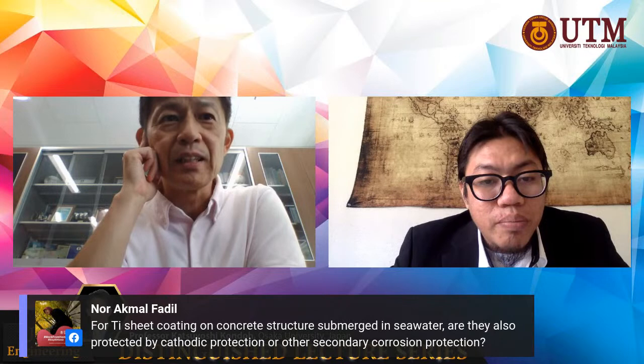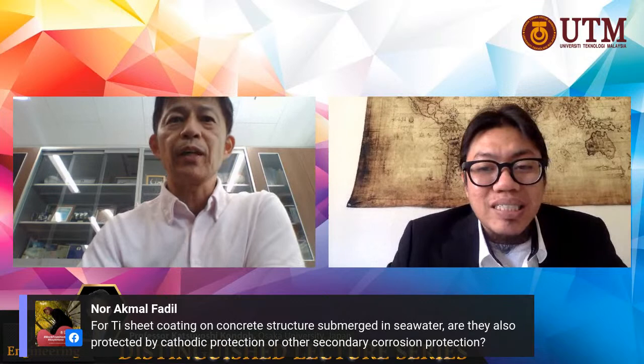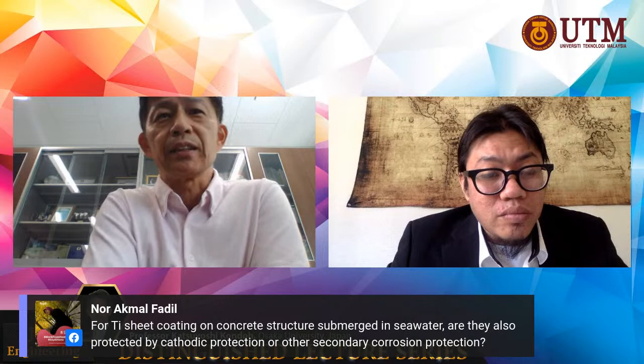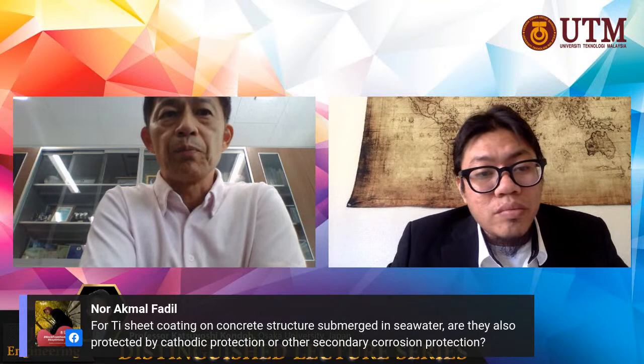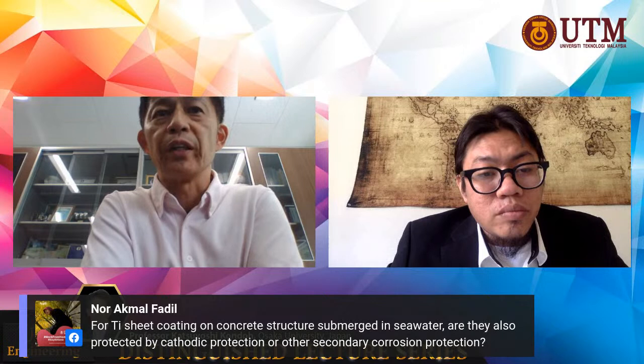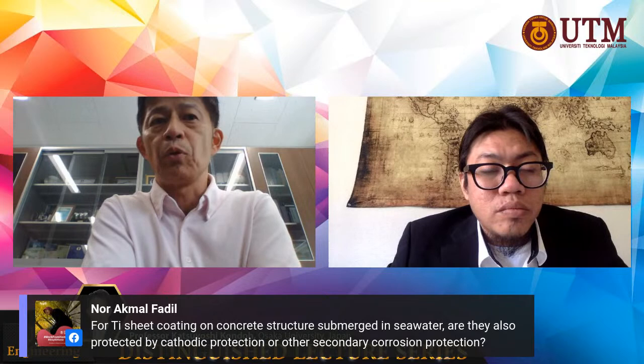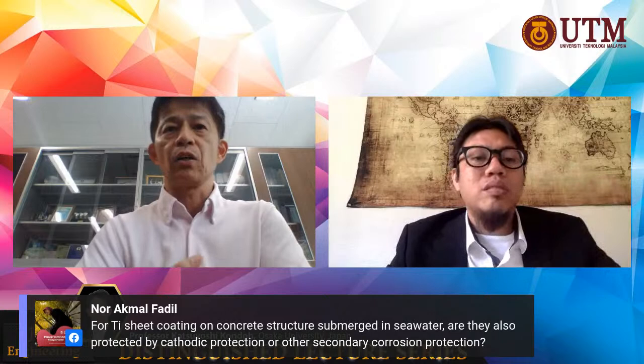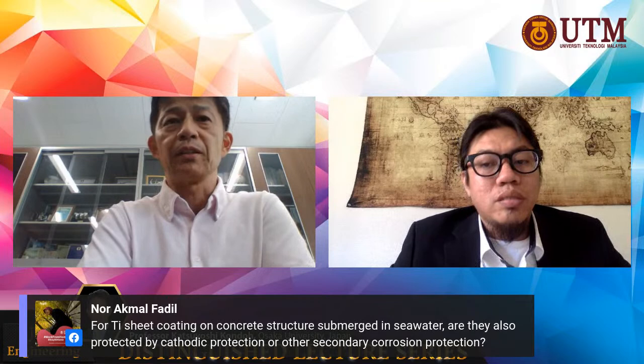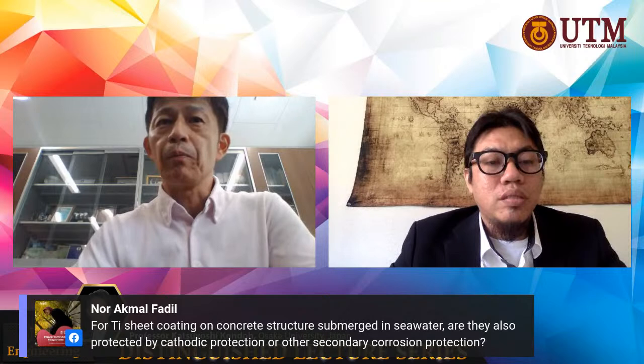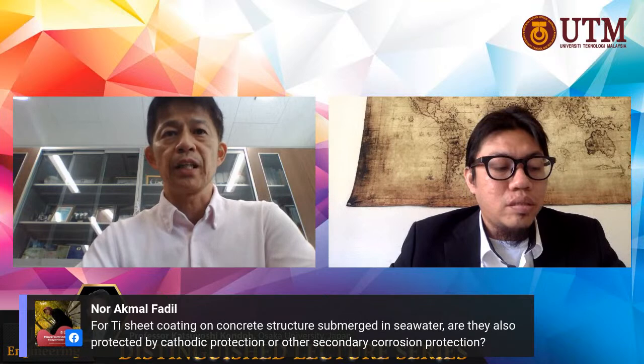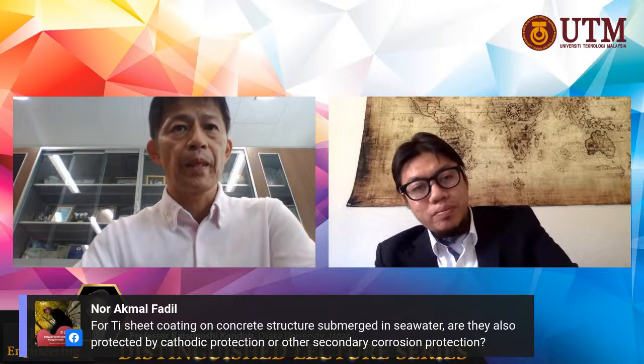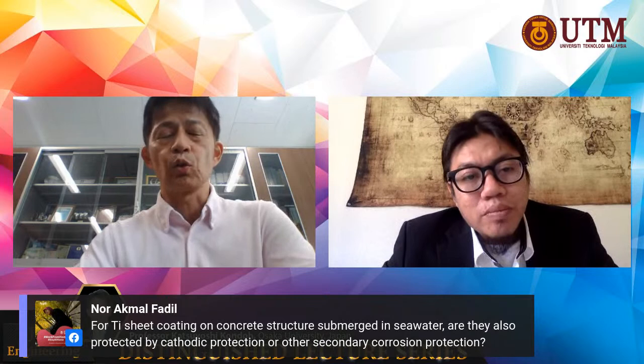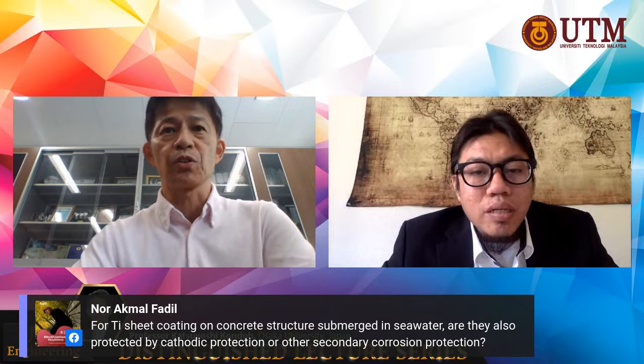Yes, that's right. But this one is a very simple idea: a concrete pillar coated with titanium. As shown here, cathodic protection is mainly the reason. But another one is that the concrete material has porous structures. The pillar contains the steel fiber and the steel reinforcement inside. So due to the coating by titanium sheet, it completely protects against the salt water entering the concrete materials through the porous structures.